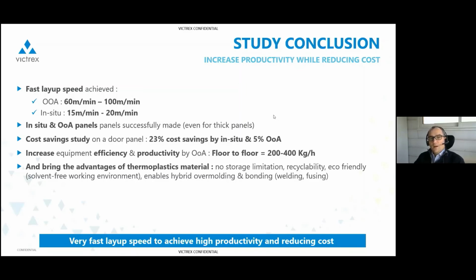But definitely we're on the right track in addressing those criteria of high speed to increase productivity while also reducing the cost. We also try to evaluate what we call the efficiency and the productivity, the floor to floor rate. This may sound pretty high, so again, happy to take this offline to give you the rationale. But when you look at those gantry machines, and how many tows you can lay up in one course, that's pretty impressive. When you combine those high capacity machines with those high speeds, you end up with a quite high floor to floor rate, which is more or less between 200 and 400 kilograms an hour.